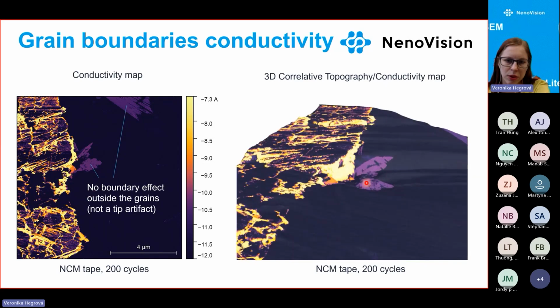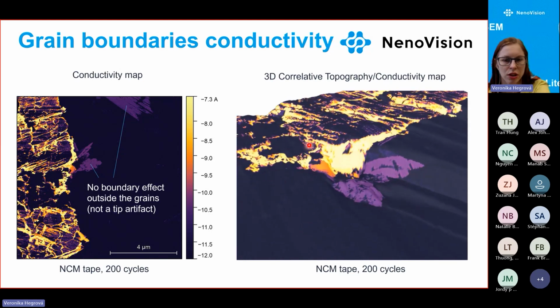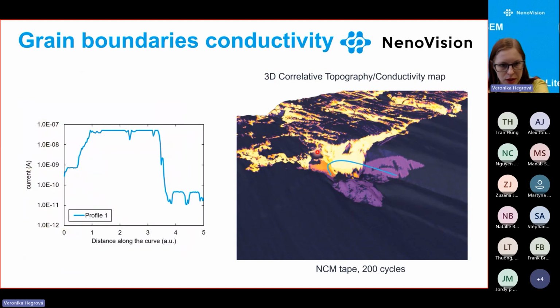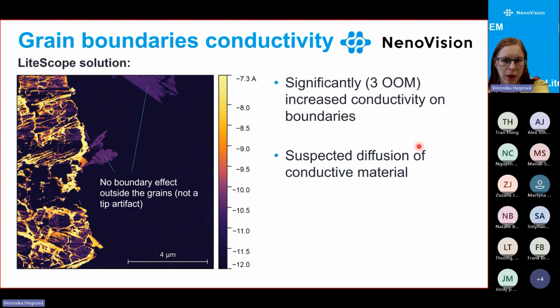And if we have a closer look over here, we see there is a large topography difference. But within the topography difference, there are several orders of magnitude difference in the current, which means that the edges are actually not a topography artifact. That was one of the questions, what it is, but it is really there. So it's the real data we are getting, and it's suspected that it's a diffusion of conductive material. So this is not an artifact of the measurement. The tip was correct. The tip nicely measured even after it, but probably something happened there.